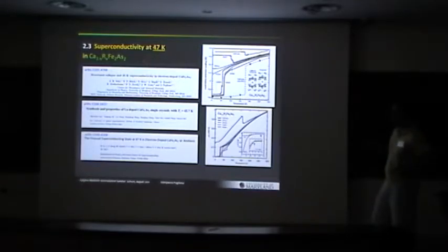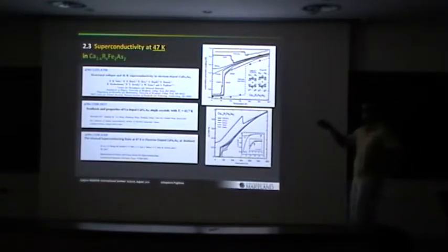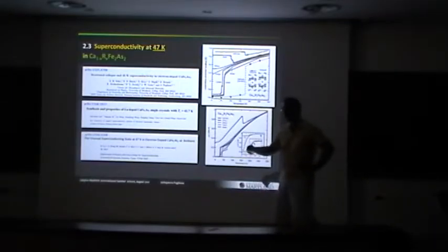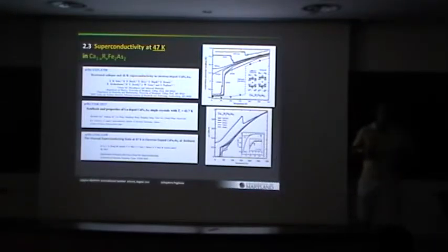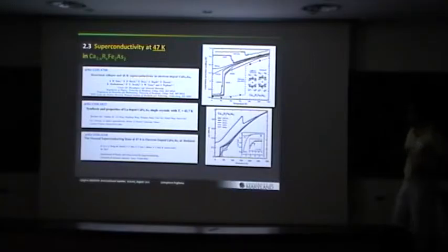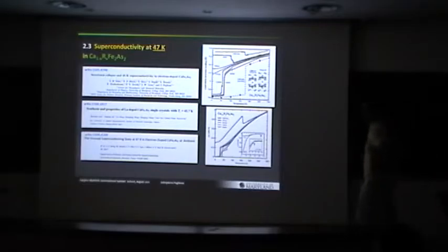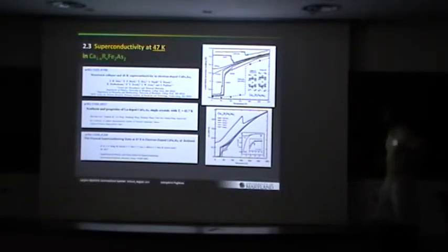There was one report of a similar compound by Hosono's group maybe 6 months ago on the strontium system. So they put lanthanum into strontium-122, and they get a 20 Kelvin superconductor there. And the synthesis there is difficult because they have to do synthesis under pressure. Here, this is all ambient pressure synthesis. Okay, so we reported this recently, and then there's a couple other papers by the Chinese group and by Paul Chu's group reporting similar results.